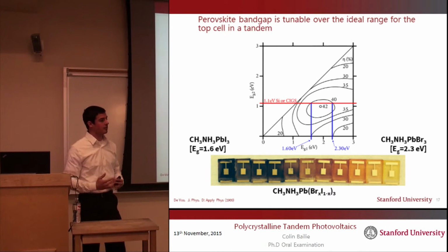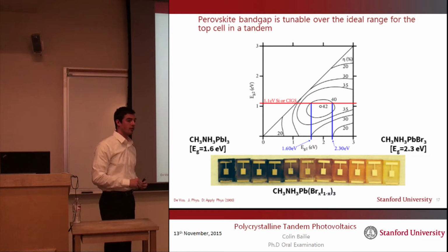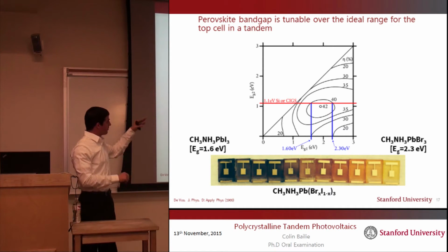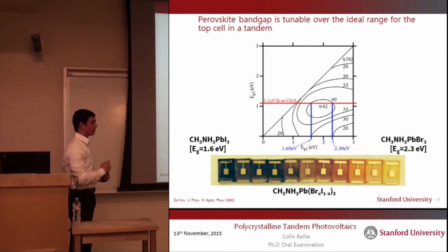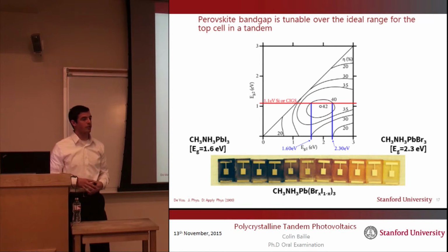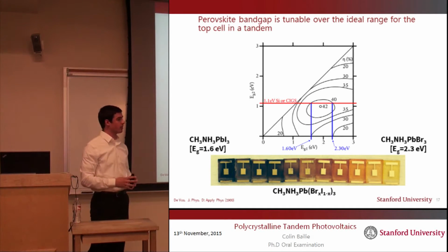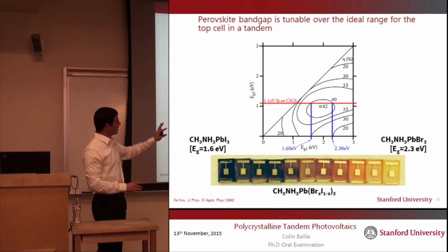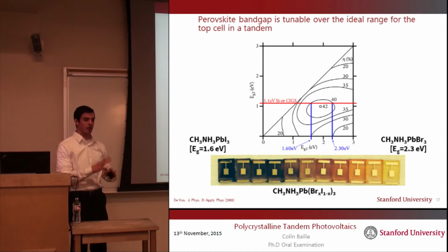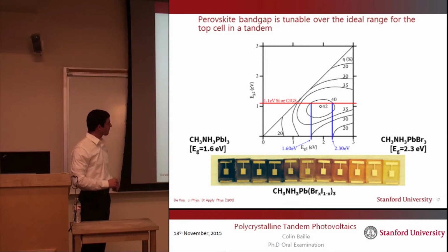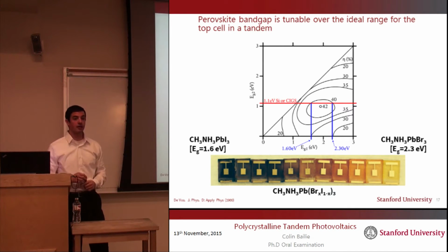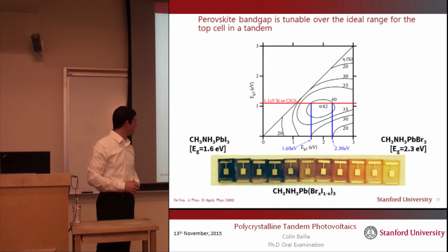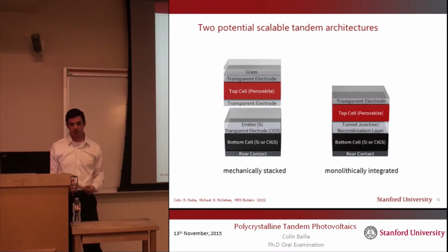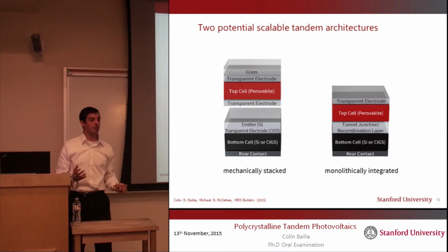There's one more requirement that has to be met in order for it to be useful in a tandem, and that is it has to pair well with the other absorber that you are going to use. So we're going to choose to use something that's already at scale. We're going to use either silicon or SIGs that has a 1.1 electron volt band gap. And if we were to do this, then we would like to have the second absorber be somewhere between 1.6 and 2.3 electron volts in order to reach this 40% theoretical efficiency contour. And it so happens that methylammonium lead iodide is 1.6 eV for its band gap, and so it is an ideal material for using as the top cell in a tandem.